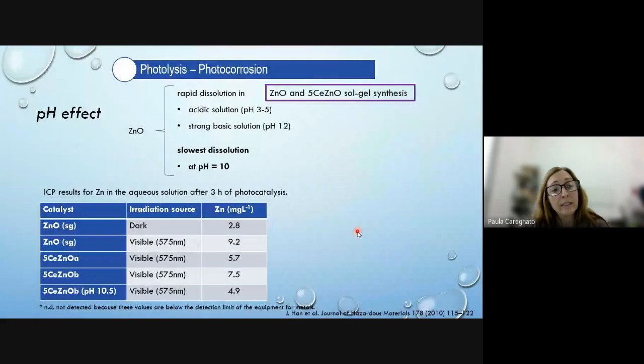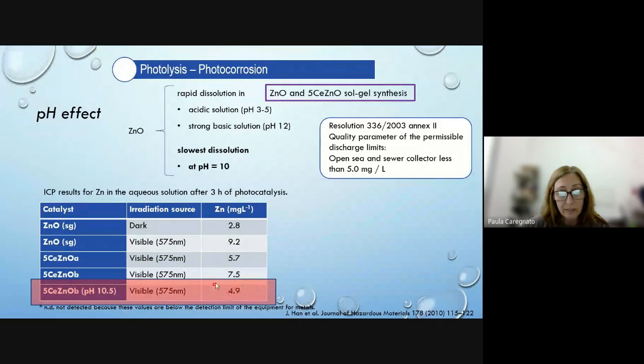In addition, we studied the pH effect in photocorrosion. In the bibliography, we have found that the slowest dissolution occurs at a pH of 10. So we developed a photocatalysis changing the pH of the reaction mixture, adding sodium hydroxide until the pH was 10. And we can see that after the 3 hours of photocatalysis, the quantity of zinc decreased, and its value is close to the quality parameter of the permissible discharge limit.